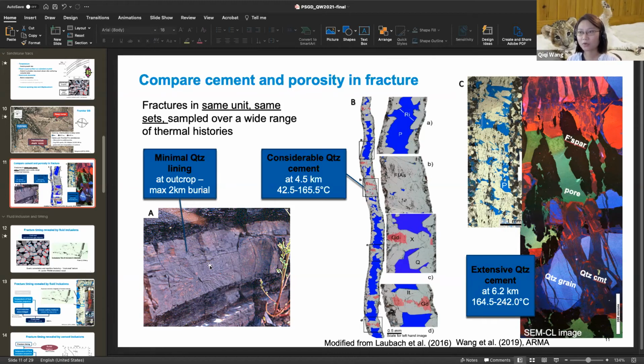Then after that, the rock got brought up to the surface and split open. That's why, present day, we can see the quartz cementation on this fractured surface at the outcrop. I'm not specifically hunting for later-stage cementation, for example calcite cementation, in these rocks, because there's probably no way I can date them, and I will not be able to know at what temperature those cements formed. It's less of an evidence compared to the quartz cementation we see on the fracture surface.